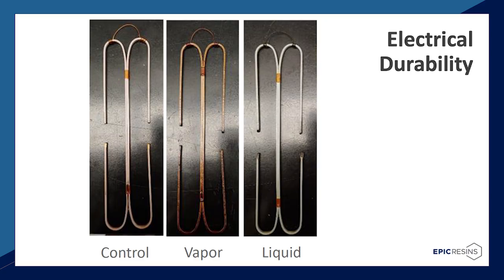In addition to mechanical durability, electrical durability in the form of dielectric breakdown was also a critical design criteria for this application. Electrical durability was tested utilizing a lashed pair dielectric breakdown test. This test is conducted by constructing a lashed pair wire test specimen as seen in the illustration, followed by the insulation process that will mimic the manufacturing process.